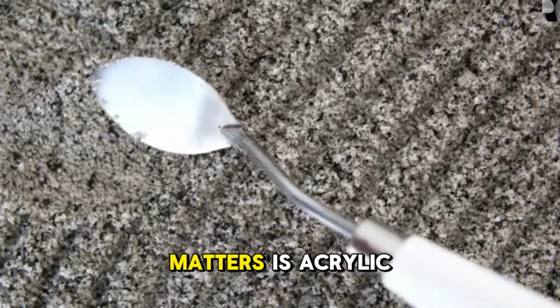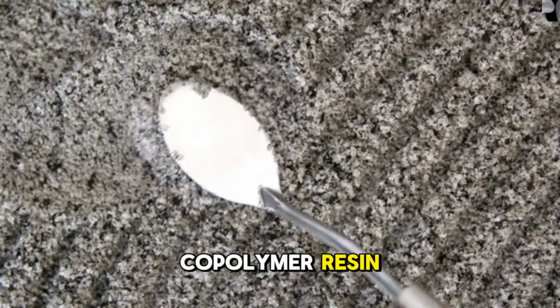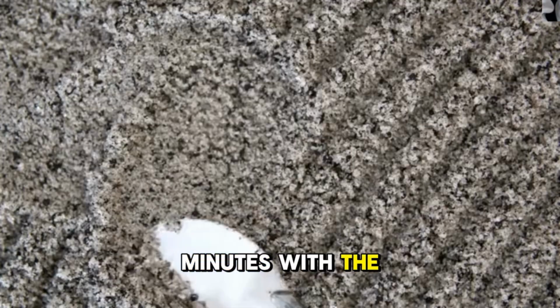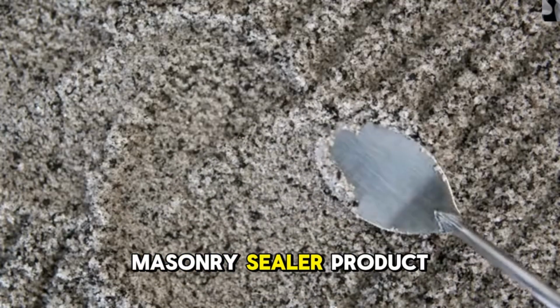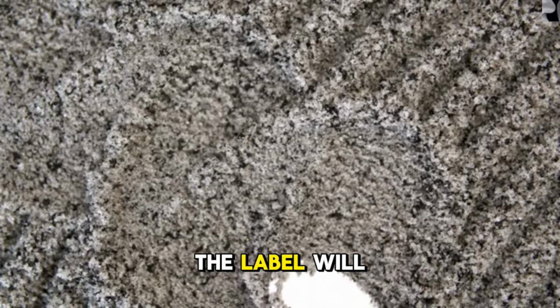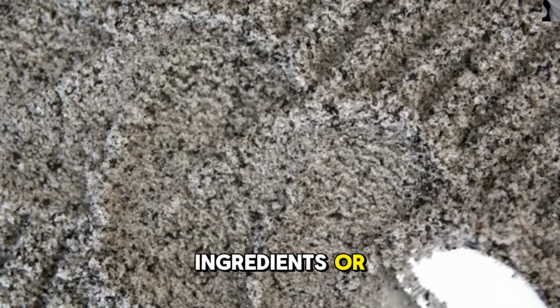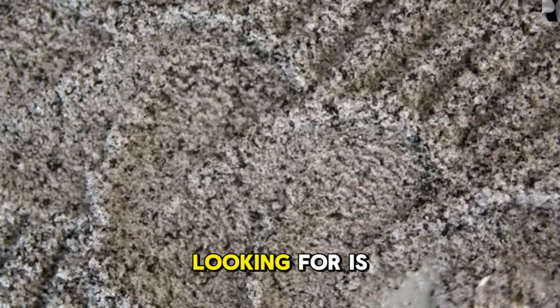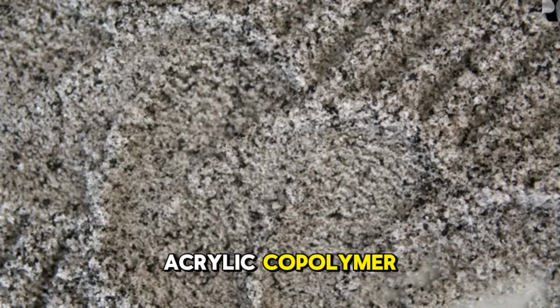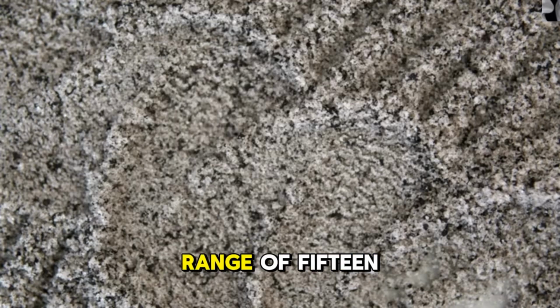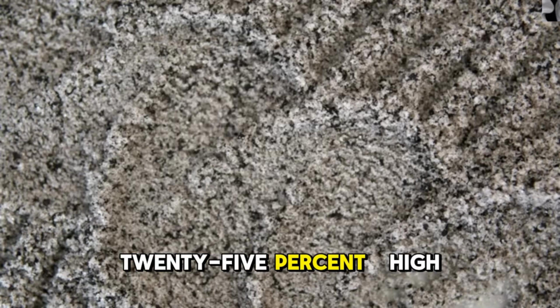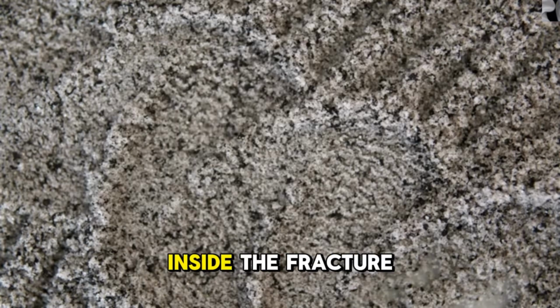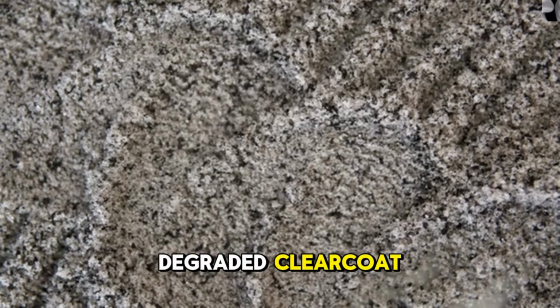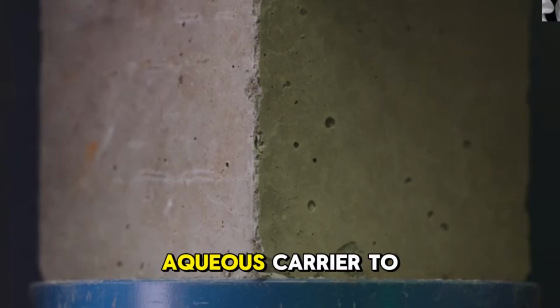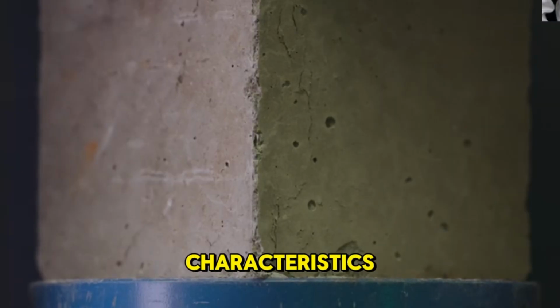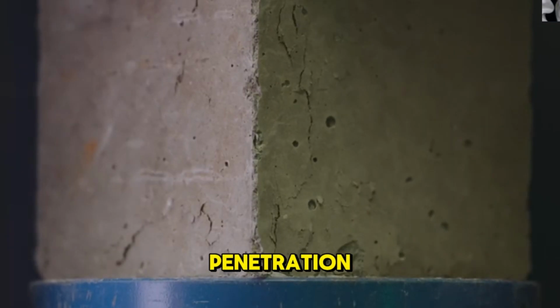The active ingredient that matters is acrylic copolymer resin, and identifying it requires only a few minutes with the label of any concrete or masonry sealer product at a hardware retailer. The label will list the active chemistry in the ingredients or composition section, and what one is looking for is a water-based acrylic copolymer formulation with a solids content in the range of 15 to 25%, high enough to deposit meaningful resin material inside the fracture network of a degraded clear coat, but sufficiently diluted in its aqueous carrier to achieve the surface tension characteristics that allow capillary penetration.